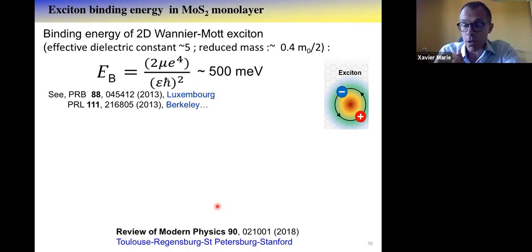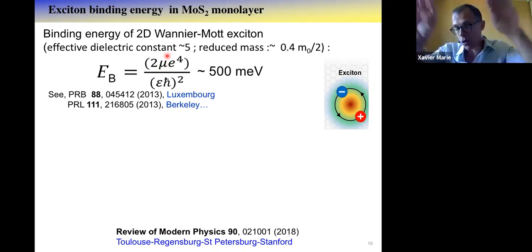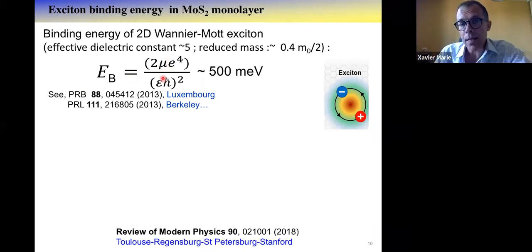why it has such a large binding energy. In fact, with a very simple formula, you can feel this. If you consider that these excitons are Wannier-Mott type, the 2D exciton binding energy follows this very simple formula, where mu is a reduced mass, which corresponds to the mass of both the conduction band and valence band. And at the denominator is the square of the dielectric constant. It turns out that in these TMD monolayers, both values will give you large binding energy.